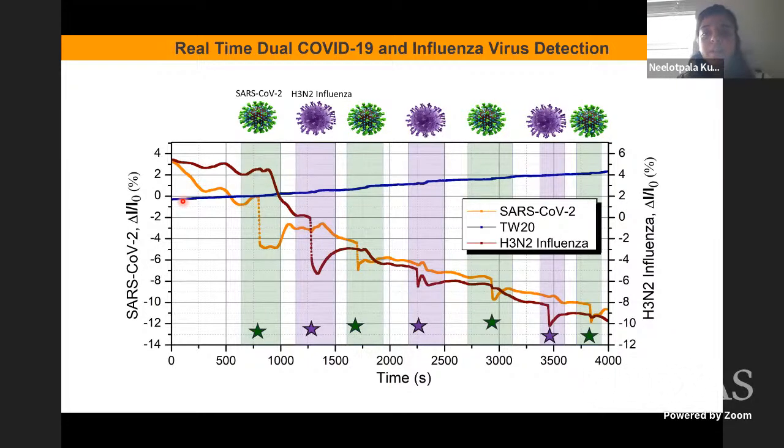Why we were using a third control, tween 20, was just to make sure that we are not reading any false positives. The expectation with this kind of chemical passivation is that nothing should be interacting with the surface of graphene. We chemically passivate the surface of graphene with everything, and so whatever we are putting in there should not influence any change on the surface.